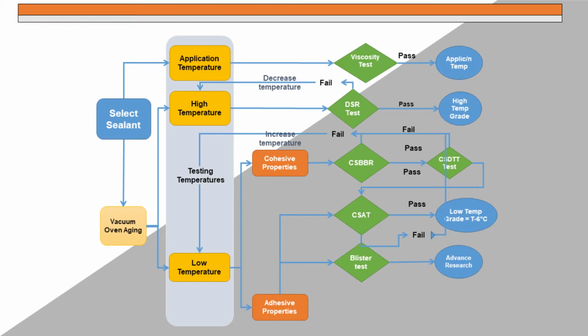Similarly, for the low temperature cracking, you will go to CSBBR. The CS stands for, any of you can guess? What CS is? Crack sealant. Thank you very much. You are very good on this topic. Very good. So, crack sealant BBR, not the asphalt BBR. And then you test. If you pass, you can go to the next test. If you fail, you will increase the temperature. So it's not that difficult to understand the flowchart, because you are already familiar with the PG grading system. All right, that was phase one.